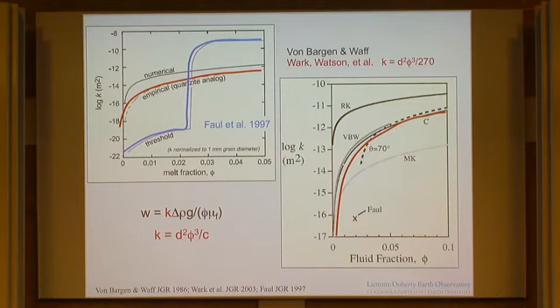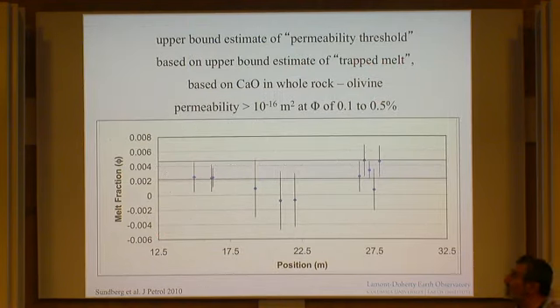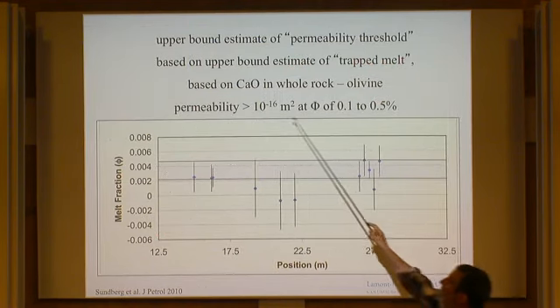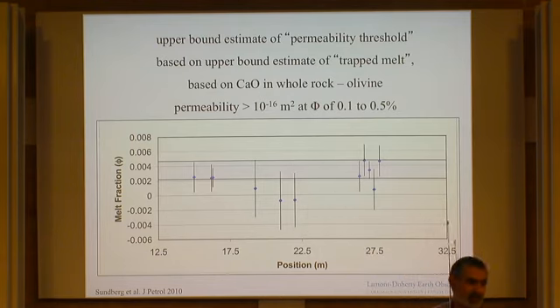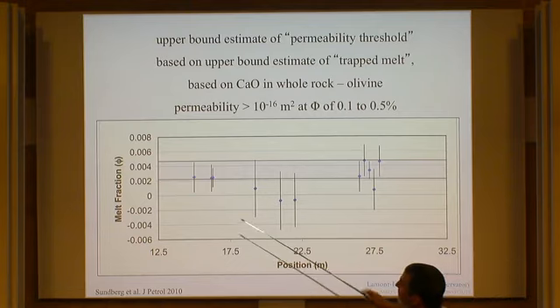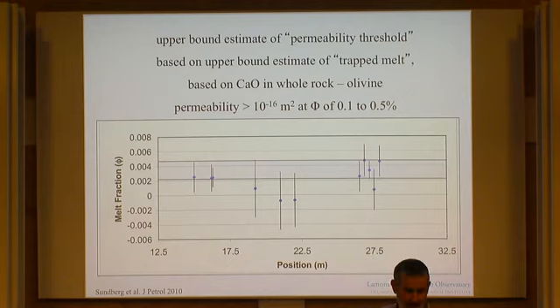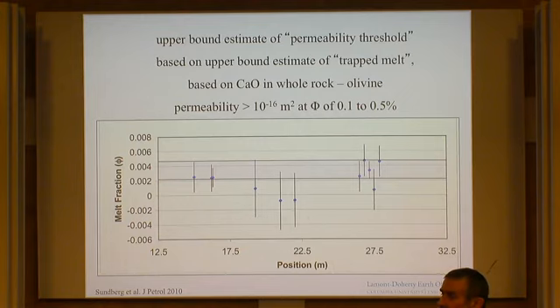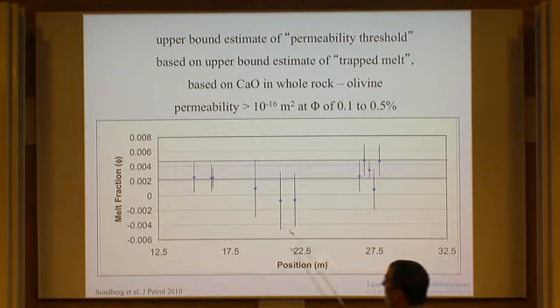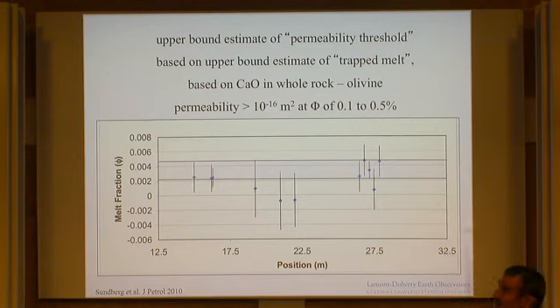And so we finally got it together to take a look at that. And we're using various kinds of chemical variables. Calcium is one that's pretty much excluded from olivine and the other mineral constituent, spinel, in these rocks. But it might remain and crystallize trapped melt on the grain boundaries. And we also use aluminum and various other things. We can analyze the olivine and the spinel in the whole rock and see how much calcium is in the whole rock that we can't account for by the calcium in the minerals, and get some idea what sort of microscopic or submicroscopic trapped melt fraction might remain in these dunites.